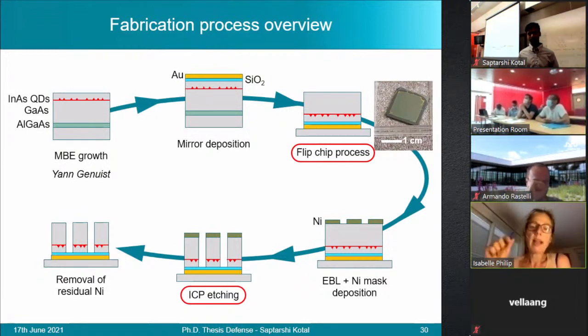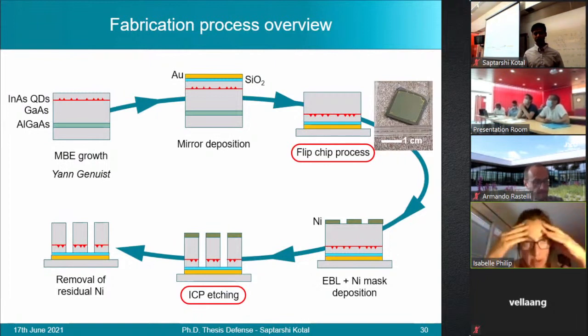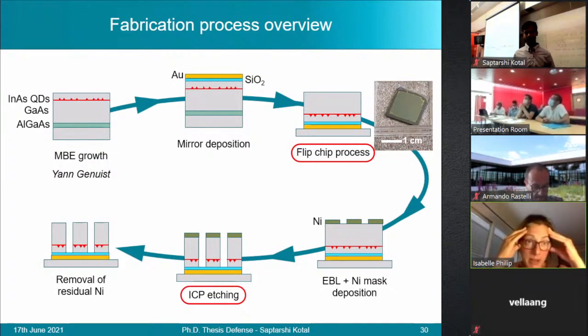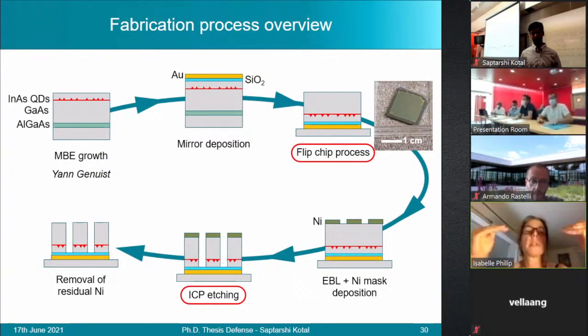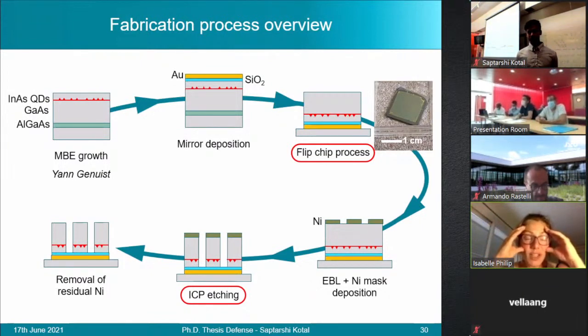Okay. Then I have another question, because it surprised me a long time ago when we were etching pillars with chlorine-based plasma. We had an issue when using just nickel masks because it was reacting with the chlorine gases, and it was becoming so hard it was impossible to remove it afterwards. So we moved towards a 2-layer mask, so that first the nickel mask was etched, and then we stopped in a resist mask that was easier to remove. You don't have this problem? The nickel mask doesn't react with the chlorine gases in your ICP process? Is it easy to remove the nickel mask? Yes, from experience, we have never faced that problem.